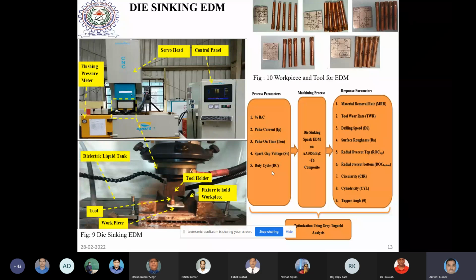One parameter is the percentage of B4C, since I have developed 5 composites. Then pulse current, pulse on time, spark gap, and duty cycle were the 5 process parameters I have chosen. Then the machining process, with the sinking medium on this composite, and the responses I have found are material removal rate, tool wear rate, then drilling speed, which is also very important, surface roughness, radial overcut, top overcut and bottom overcut.